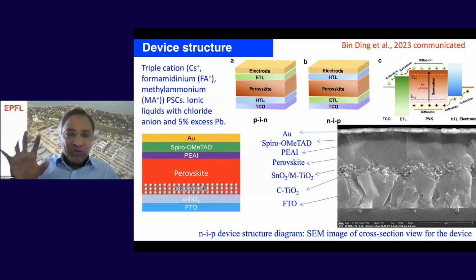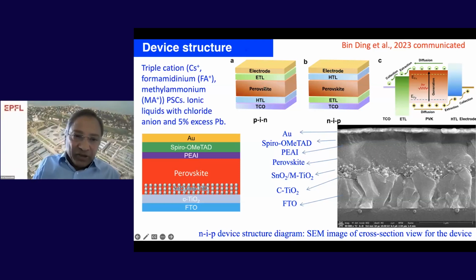Once you have a perovskite film, you can form two types of solar cells. One is called PIN, where the perovskite is sandwiched between a hole transporting layer and an electron transport layer. The light is coming through the hole transporting layer, so here the hole transporting material has to be colorless. In the other configuration, NIP, the electron transport layer is deposited first, typically TiO2 or tin oxide. These oxide materials are colorless, so you have transmission of all the light to be absorbed by the perovskite layer.